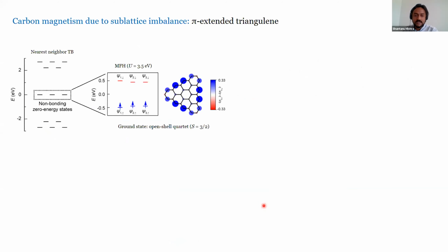And now what one expects from the electronic structure of this molecule is that you have 3 zero energy states in the tight binding spectrum. And once you include electronic correlations, you have the opening of a Coulomb gap, and you have 3 singly occupied orbitals, psi1, psi2, and psi3, and they're all occupied with the spin of the same kind, so spin up, and the corresponding spin down counterparts are empty. And that's the spin polarization plot. So if one has to detect magnetism in such a compound, there are 2 things to do. The first is one should be able to experimentally detect the opening up of this Coulomb gap. And second is that given the molecule should have a quartet ground state, so spin 3/2, one should be able to find a quartet-doublet spin excitation, if you will.